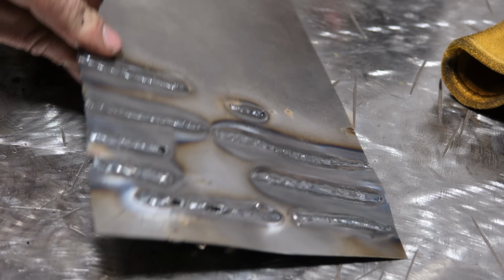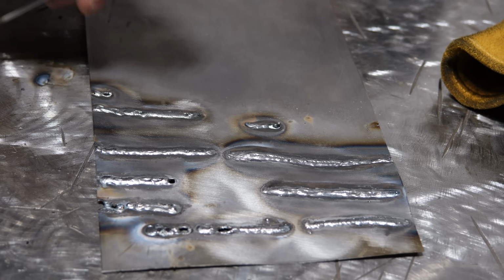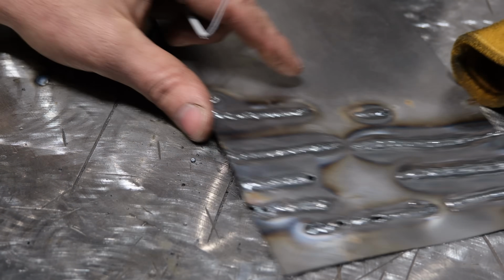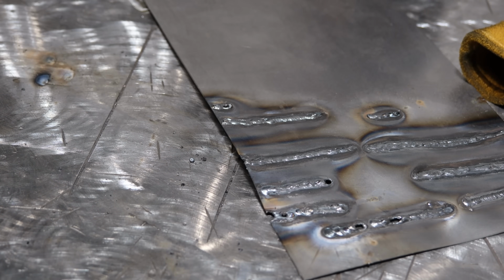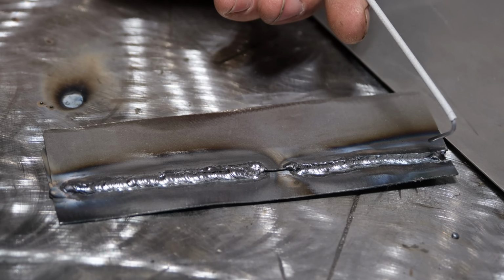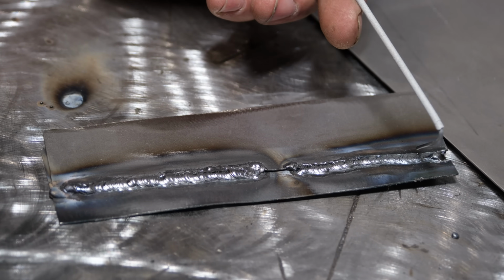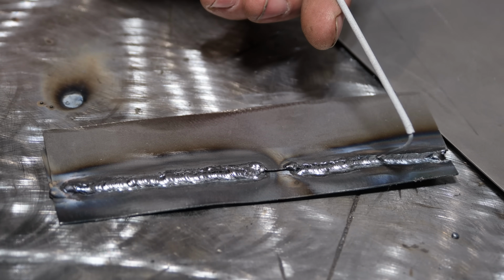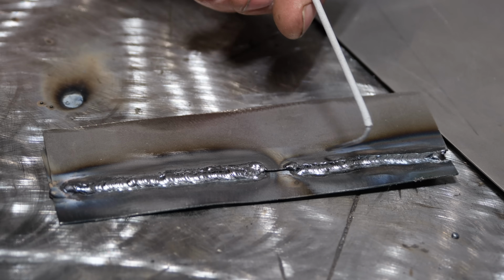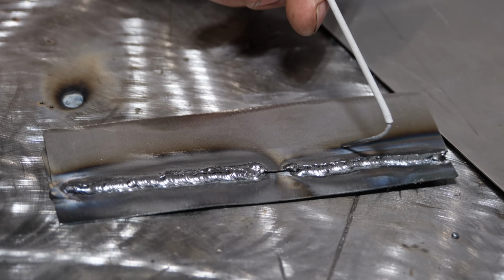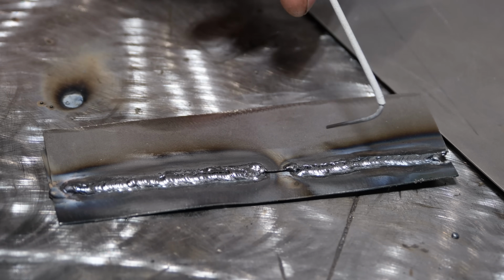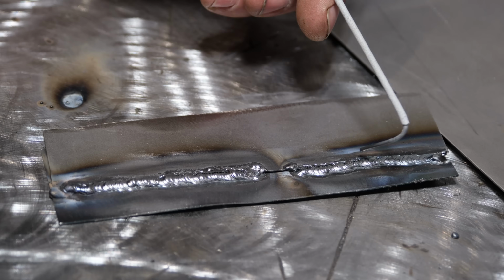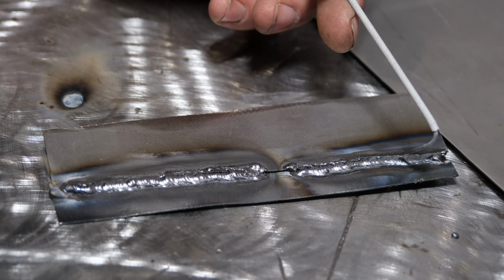So I was pretty confident, even as ugly as this junk looked, that I could probably make a weld. Let me show you what I came up with. So this is 6011, my first shot. I was fairly successful for an inch or so, and then it's so difficult to get it to wet out to this top plate without just blowing it away. I tried a couple different rod angles, but I was somewhat successful.